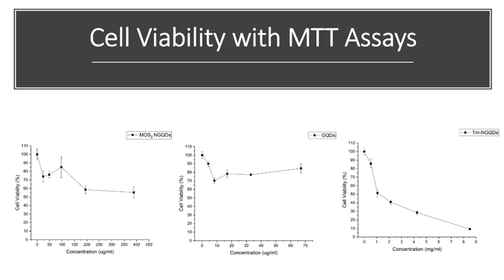What's important to know here is that when these cells come out of the incubator and you give them the MTT and then put the DMSO in there and run them through the experiment, they're out of their happy place for a long time, so they're going to die a little bit. So we had one control sample for each of these tests, and it only had DMEM in it, the medium the cells live in. However many of the cells were alive in that was counted as our 100%, and everything else is in comparison to that one sample.